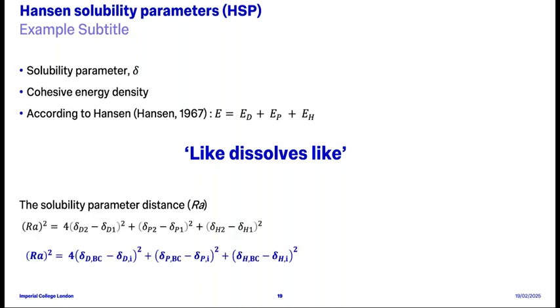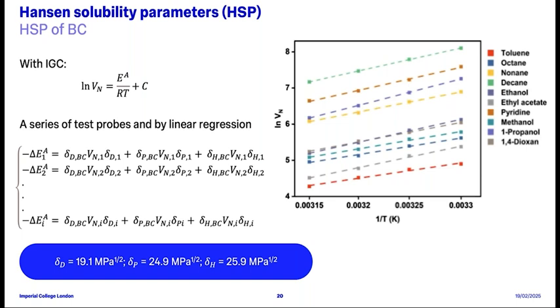To indicate how close the solubility parameters of two components, in our case bacterial cellulose and the respective solvents, are to each other, the solubility distance can be calculated with the equation shown here. While the components of solubility parameters of different solvents can be found very easily from different databases, the solubility parameters of bacterial cellulose are seldom reported. So here we're using an indirect method to estimate the solubility parameter components with the aid of inverse gas chromatography. By using a series of test probe molecules and by linear regression of the retention volumes at different temperatures, the partial solubility parameters of bacterial cellulose can be estimated to be around 19 for the dispersive component, 25 for the polar component, and 26 for the hydrogen bonding component.